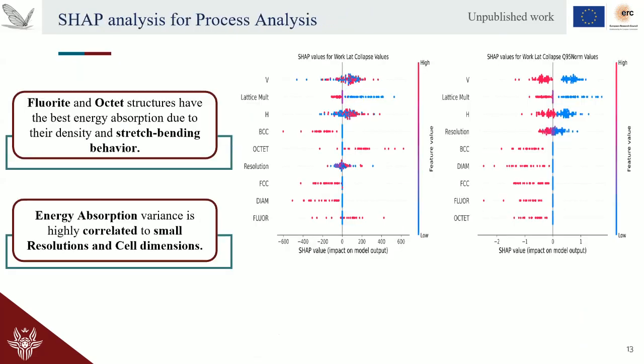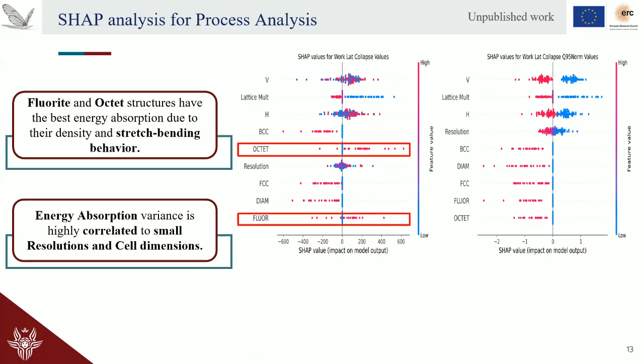So once I've demonstrated that this model is actually accurate, I can also use this kind of modeling solution to investigate the inner mechanics of the process that I'm observing. For example, here, by using SHAP values, I can extract how input parameters affect the overall toughness and the overall scatter of the toughness of the materials. And for example, we can see here a positive interaction for the octet and fluorite cells, but that's no wonder because they are very dense and they have a mixed bending and stretching behavior.